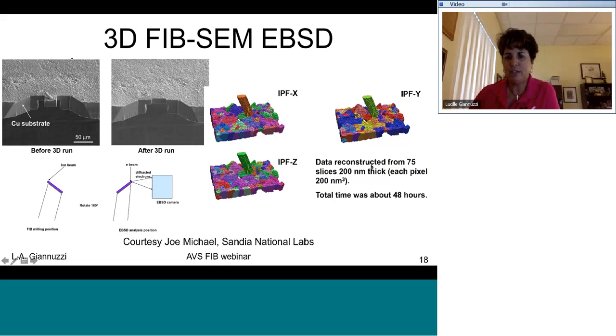So this is data reconstructed from 75 slices, 200 nanometers thick. Each voxel is 200 nanometers cubed. So the total time is 48 hours. So that's a lot of instrument time. These types of things are generally done over the weekend, for example. And again, when you start to consider how many slices there are, and the amount of time that the electron beam spends either collecting an image or an EBSD pattern or an EDS pattern, you can get into tens of hours of acquisition times. And so this can be quite lengthy.